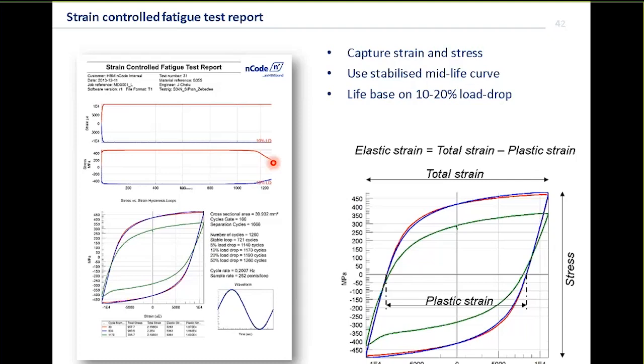The load drop's occurring because a crack's starting to grow, and so it requires less load to achieve the same strain. And if we plotted the stress-strain hysteresis loops, we can see that in the green one here, look. So the strain amplitude, the difference from left to right, is always kept constant. But the load it can carry is reduced simply because the crack's forming. And we see there's a different shape to that in the compressive region here, where the crack closes and comes together, from when the opening one, where we're opening up that crack.